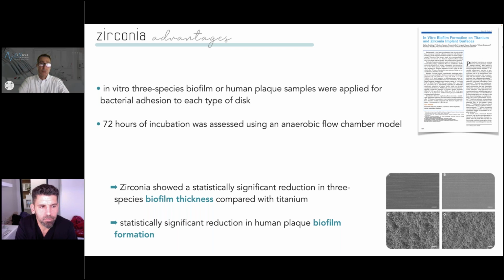In this particular study, it was an in vitro study where they took 3 species of biofilm and human plaque samples, and they were applied for bacterial adhesion to different types of discs. And as you see in the image on the bottom right, they had smooth and rough titanium discs and then smooth and rough zirconia discs. These were incubated for 72 hours.